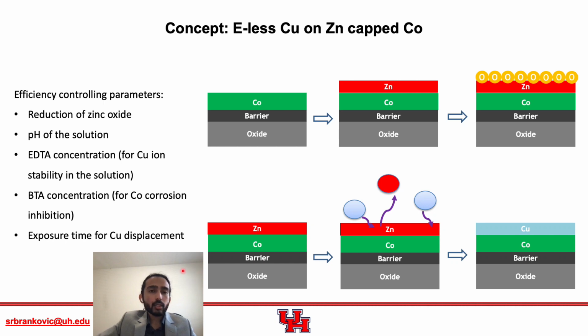So the process schematics are shown here. First, we start with cobalt and then we deposit zinc. And once the wafer is taken out of the PVD chamber, there would be zinc oxide present on the surface. So our work at University of Houston starts from this step. First, we need to reduce this zinc oxide to the metallic zinc so that it could be replaced with copper. During this, these are the critical parameters which we need to control